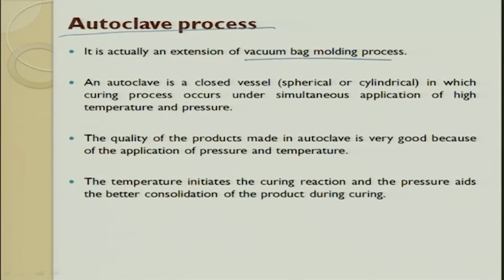It is an extension of vacuum bag process. It is a closed vessel, depending upon the temperature and time. Generally here for polymer matrix composite, the temperatures we always operate at are somewhere around 150, 200 maximum, and depending upon a very rare combination of polymer, we can go up to 300, 400. The pressures generally range from 1 atmosphere and can go up to 10 atmosphere or 20 atmosphere, depending upon the consolidation, depending upon your structural use of the polymer matrix composite.